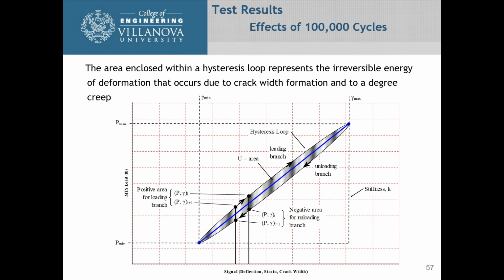Just to give everybody a little education, the area enclosed within the hysteresis loop represents the irreversible energy of deformation that occurs due to crack width formation and to a degree of creep. So that area there inside here represents the loss of strength. What you have is your stiffness, and your stiffness is the slope of this line from the minimum load to the maximum load and what your crack widths were or deflections.